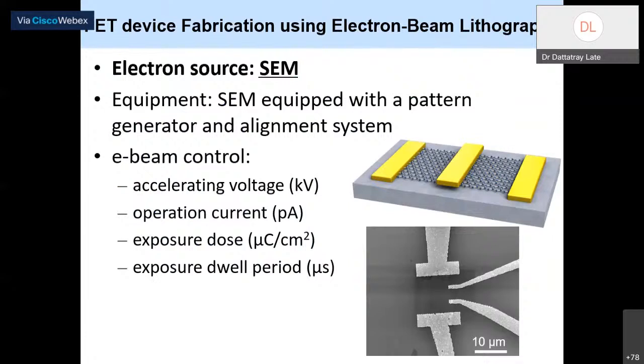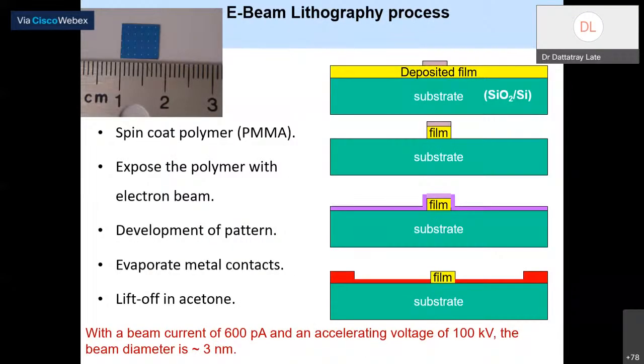We also tested the device, same material, same thing. We tested in another way. We prepared a field effect transistor by using electron beam lithography. I will not go into detail on how you can make a device using electron beam lithography, but briefly, we need a SiO2 substrate. We can deposit polymer, expose the polymer with electron beam, and develop the pattern. Once we have developed the pattern, you give contacts of source, drain, gate, and you can lift off the material whatever you have coated, and then once you are done, we have devices ready.